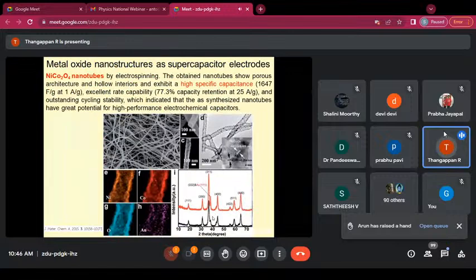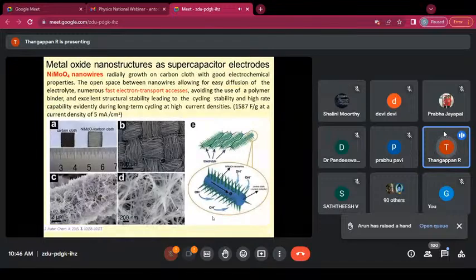Here are some examples of metal structures for supercapacitor applications, such as nanotubes. Nanotubes have 77.3% efficient charge retention and capacitance values of 1647 farad per gram, and tube-like structures are formed. Then there is carbon cloth, where the carbon material is coated on the surface of the carbon cloth for supercapacitor applications. It has 1587 farad per gram, and fast electron transport also occurs successfully in this kind of structure.